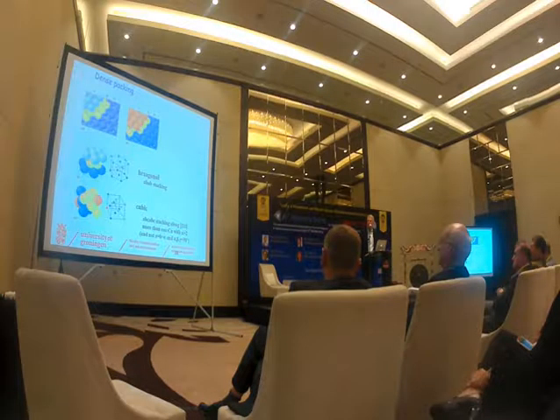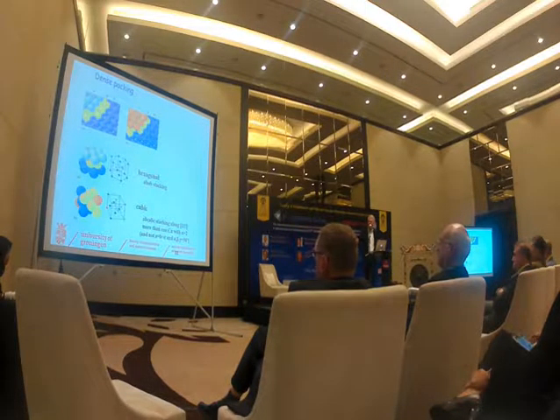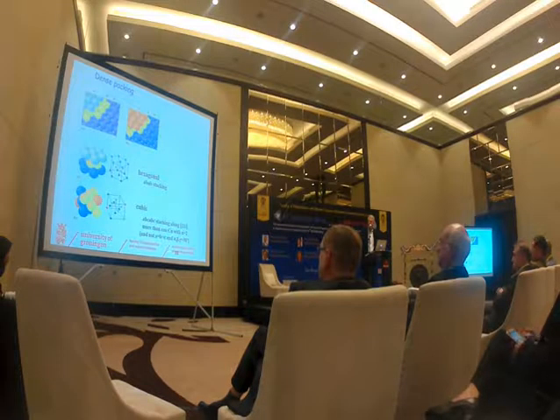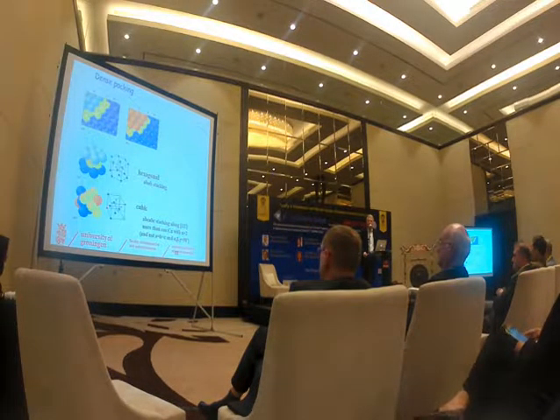If you do the bonding with dense packing, there are two types of packs. One is a cubic dense packed, called the face-centered cubic structure, or the hexagonal close packing, which is an AB stacking of such dense packed layers. This is the basic principle of any inorganic material. But you also readily see that inside these materials, all these materials always have inversion symmetry, almost by definition. The coordination of these packings of octahedral, tetrahedral, some of these octahedral environments always are based on inversion symmetry.